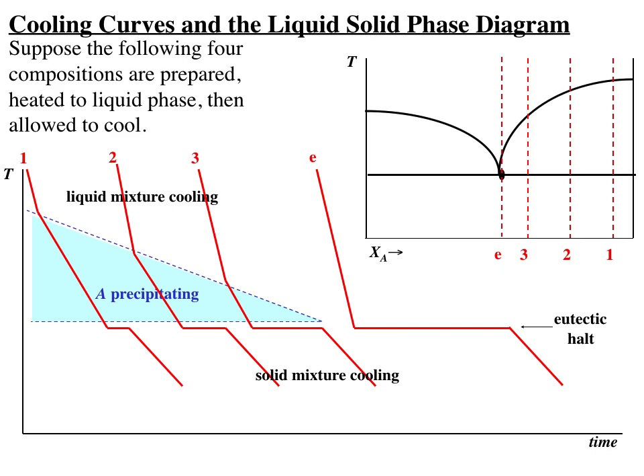Now notice after the entirety of the eutectic mixture has solidified, I can go again after a discontinuity to cool the solid mixture of composition E. And that's a nice linear function, a diagonal line showing cooling the solid. All right, now let's go over to curve number 3, the next one over to E. This, you will note, by composition has the minimum amount of A compared to the amount of B. So that has the XA3, the smallest of the remaining compositions beside the eutectic.